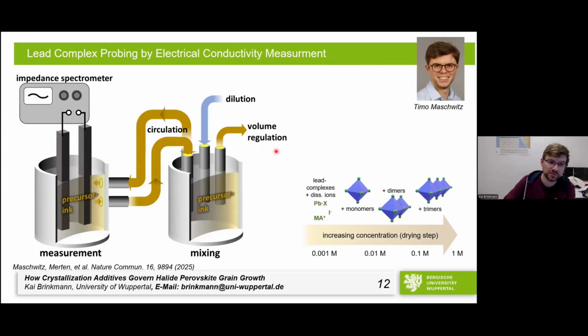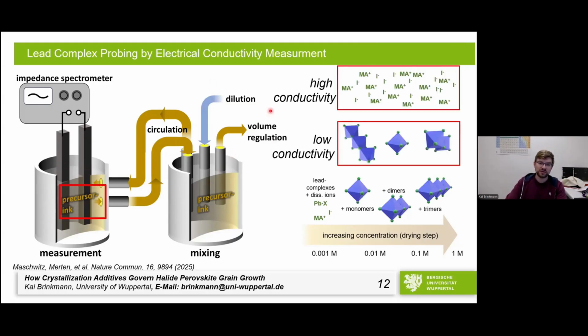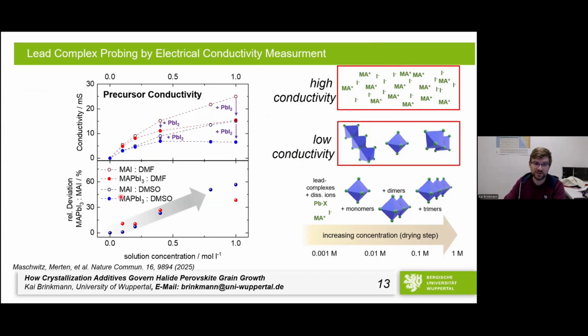Another technique that we used to probe this was simple conductivity. So basically we did an AC field. We put two carbon electrodes, we applied an AC field, and we had a circulation pump so that we can change the concentration in this part here. We just had the idea that if you have a lot of small ions flying around in the precursor, this should give you high ion conductivity. The other way around, if you have these large complexes, this large multi-trimer, quadrimer, whatever it is, species flying around, the charge to volume ratio is lower, and you would have lower conductivity. And straightforwardly, this is the case.